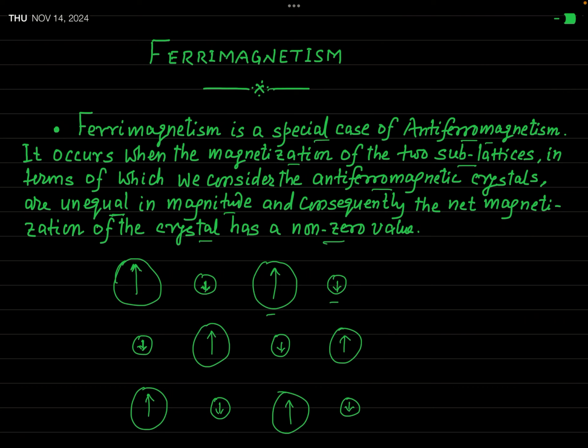In fact, if the magnetizations of different sublattices do not cancel each other in an antiferromagnetic spin array, there appears a kind of ferromagnetism as a result of antiferromagnetic coupling, and this is termed ferrimagnetism. The well-known scientist Neel pointed out that the ferromagnetism of ferrites is due to this mechanism.